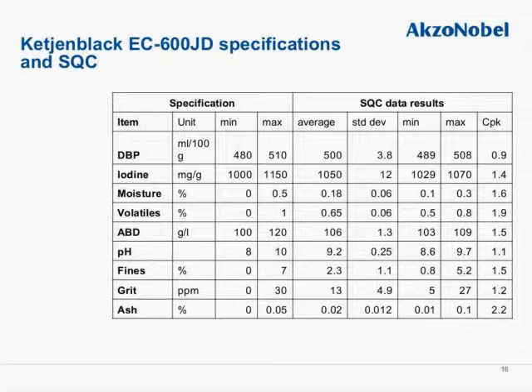The specifications for Ketjenblack EC-600JD are again very similar, except for the first two that are indicating the surface and pore volume. The same very low moisture, which keeps the integrity of the pellets until they have to be dispersed into the polymer matrix, as well as low volatility. And just like Ketjenblack EC-300, again, we have a very low grit and ash content, which can ensure that the products are used in applications where high purity is required.